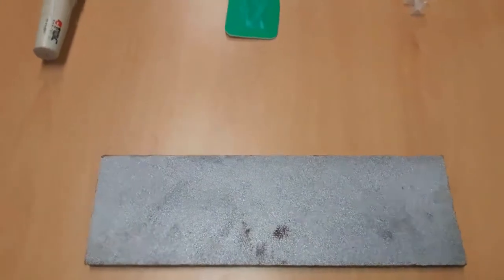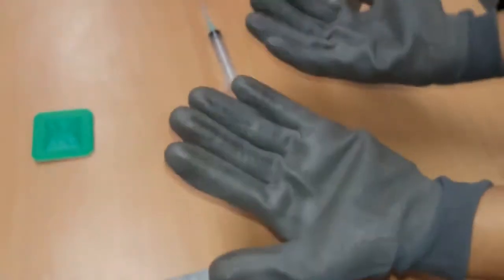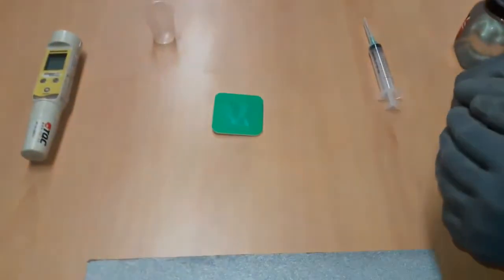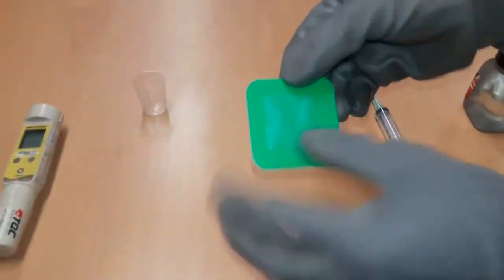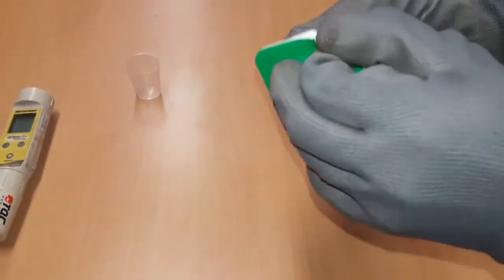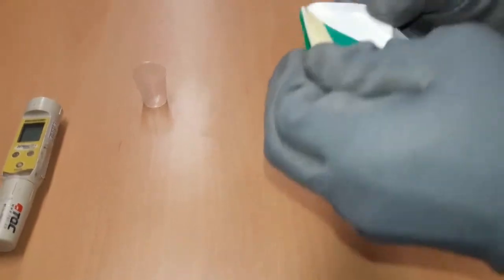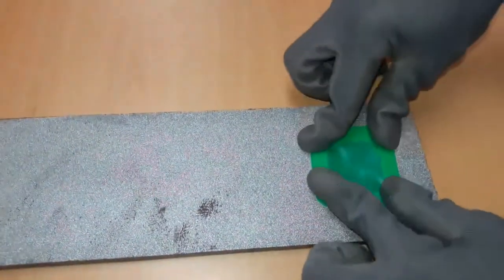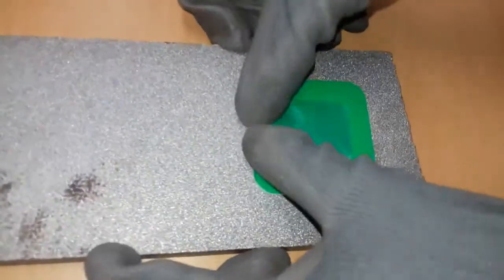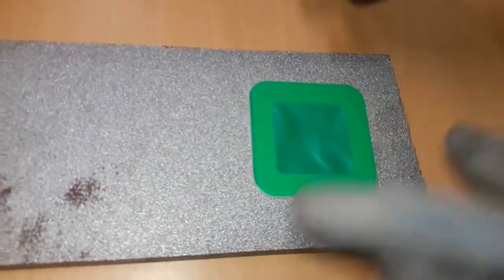Procedure. Wear rubber gloves during measurement. Take the adhesive patch. Remove the protective paper and punch out the material. Press the adhesive patch against the test surface in such a way that the minimum amount of air is trapped in the compartment in the patch. Fill 15 ml of solvent in the 25 ml beaker.